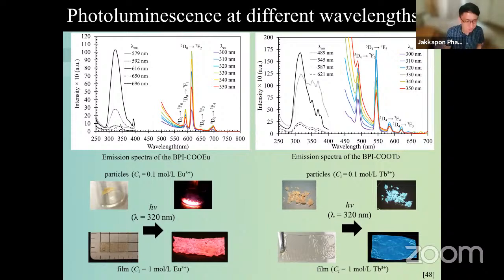It's a very wriggling polymer. But you see, the polymers actually have much brighter light. When you put it in the polymers, it's called the antenna effect. The antenna effect will create a brighter fluorescence light when you add some kind of ligands into the lanthanides. The lanthanide itself is not so bright, but when you put in ligands like the polymers over here, you create a much brighter photoluminescence, and it can also be used in the sensor.